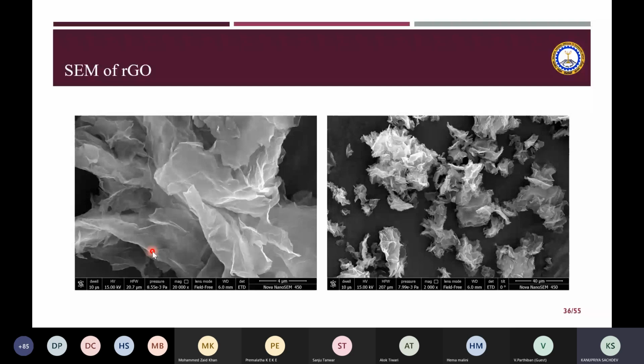This is the scanning electron microscope image of the reduced graphene oxide. So you can see that these are the layers. We have a large number of layers here, and they are wrinkled. They are not very smooth. So this is the usual morphology which we get in reduced graphene oxide. And this wrinkled morphology is useful in the sense that it gives a very high surface area, making it useful for sensors and other applications.